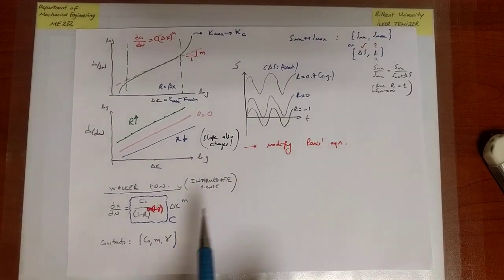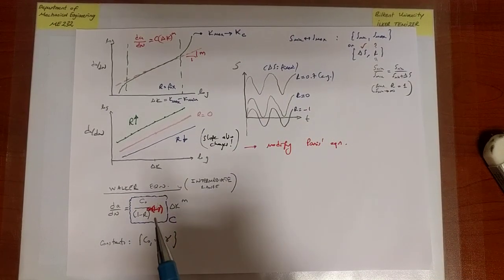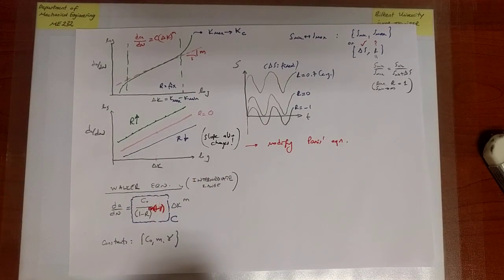Okay. So in some sense, the Paris equation gives us a stencil, a template, but really you wouldn't use it in reality. What you would directly use is the Walker equation, because the Walker equation is the natural generalization of the Paris equation towards the incorporation of R, which is the second most important parameter in the load profile after delta S. So this equation has everything that you need to model the crack growth rate if you can ensure that you are in the intermediate range. It works very well. All right, so that is essentially what we have presently.